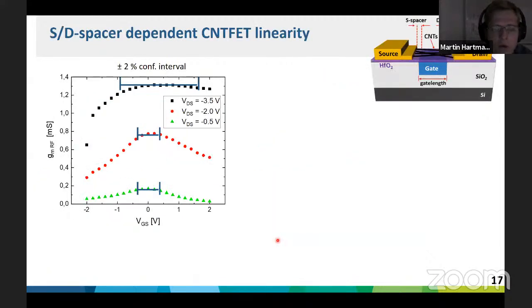And now we took a look at our results, whether we could confirm this. And first of all, we looked at this linearity, or at the constant region of the transconductance for different bias voltages. And we found that if you increase the magnitude of the bias voltage, your linearity or linear region increases. And this is due to mutual screening effects.